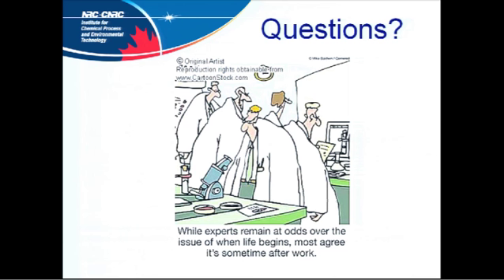Well, this is something you have to deal with at the data collection point, because it's one of these things that you cannot fix afterwards. This again crops up in data collection. Actually, the book that Kenneth mentioned yesterday on data collection for structure solution does cover this in quite good detail. The general rule of thumb is you want the step size to be no larger than the full width half maximum divided by 5. So a one-size-fits-all experiment doesn't work.